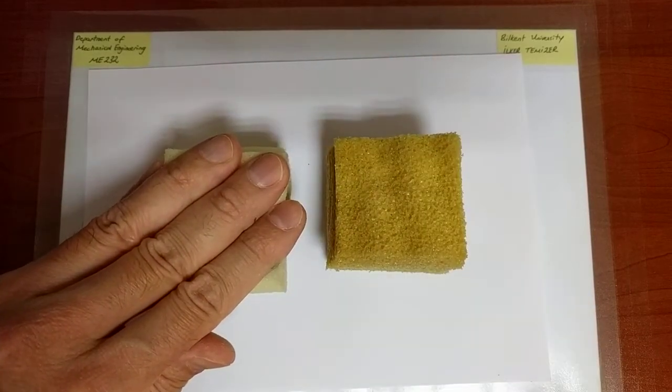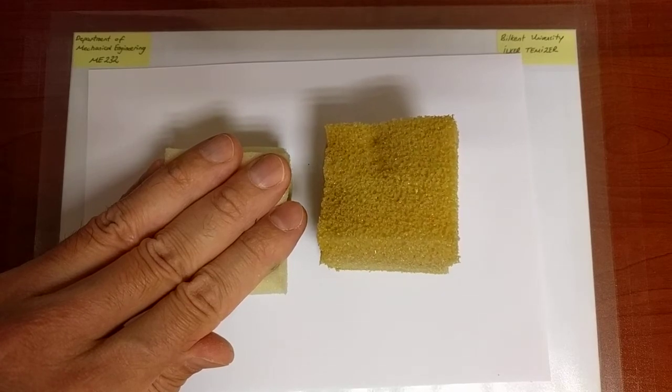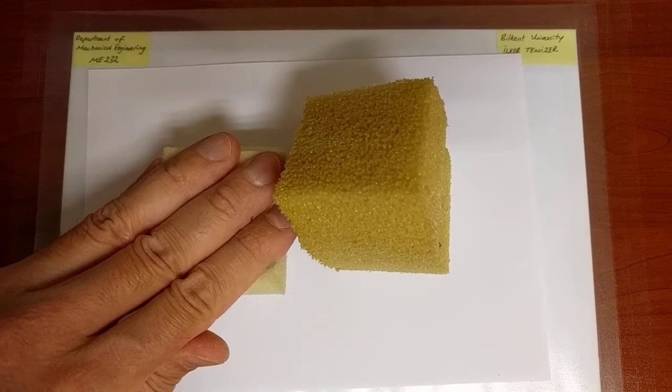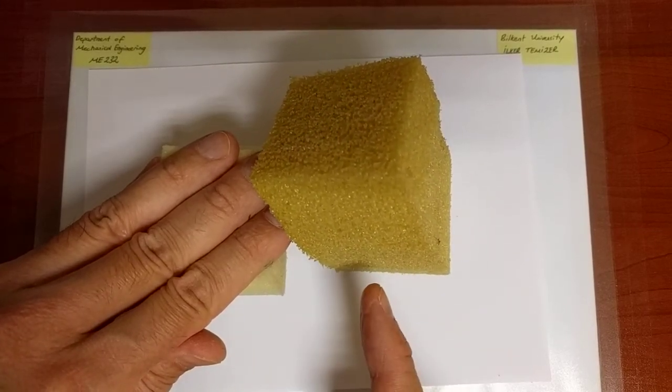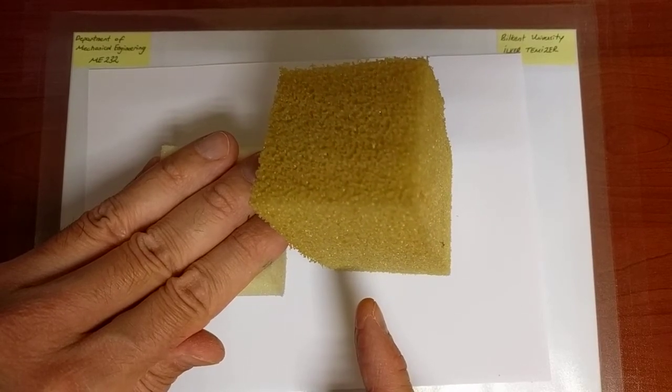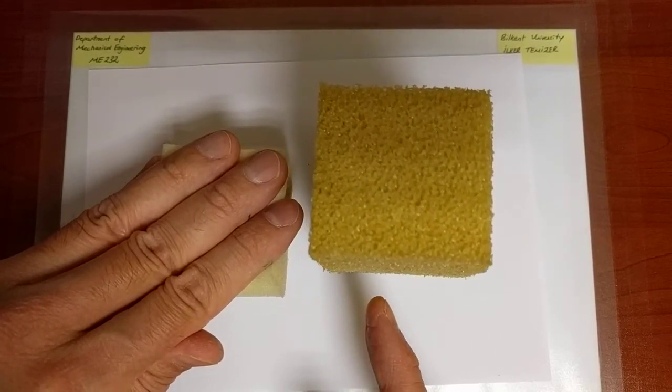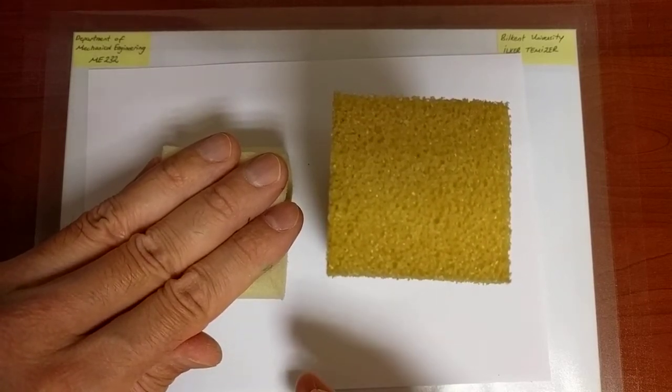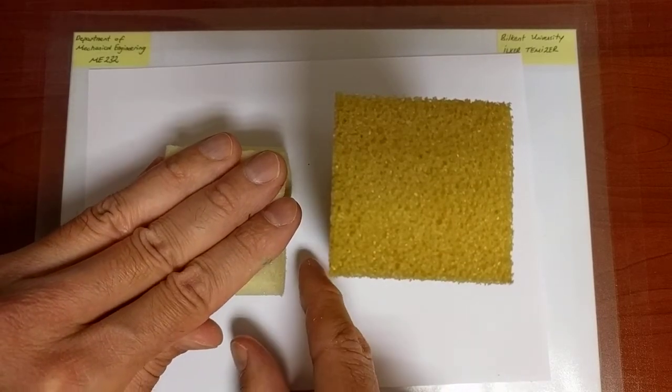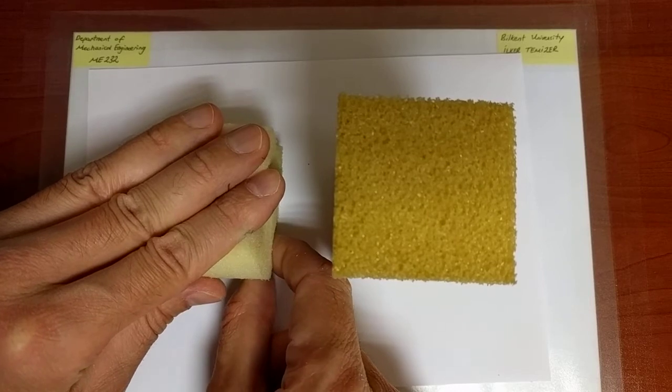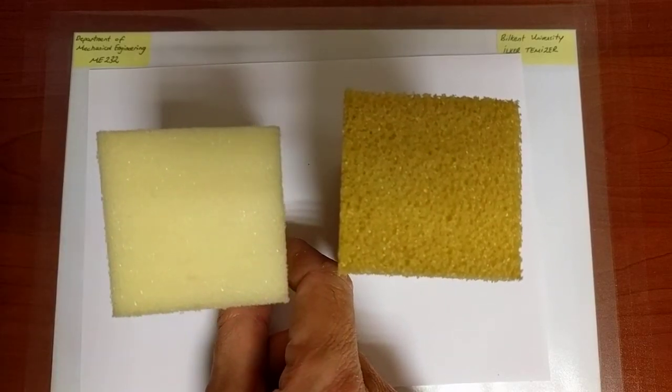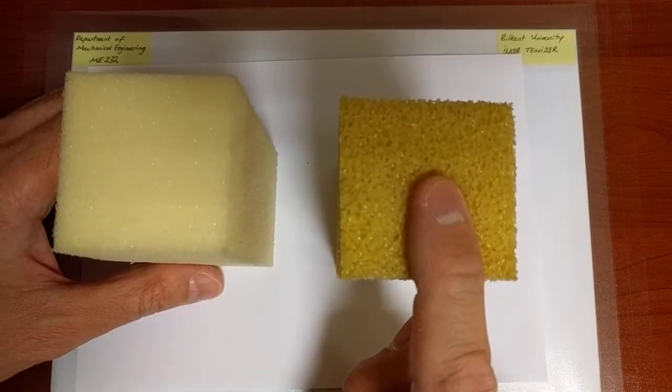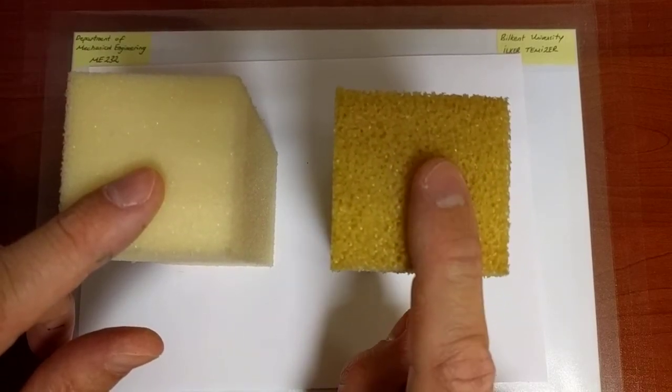Now, first of all, I let the right one go. And what you see is it takes time for it to deform. Apparently, the response time of this thing is quite large, it's probably of the order of, if you're watching the video, maybe close to the order of 10 seconds. It took about 10 seconds for it to respond significantly. Now, 10 seconds, with respect to what? Watch here, I'm going to release this one. This one immediately responded, so what's the characteristic response time of this? Probably less than a second, whereas this one, it's much, much higher.